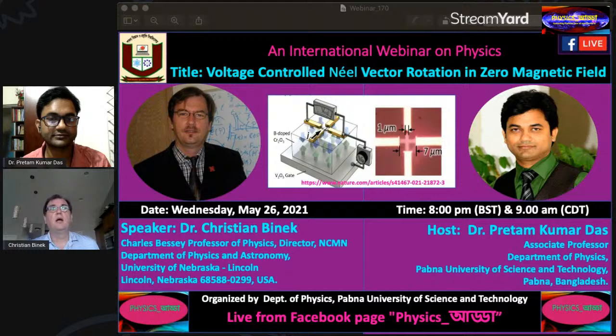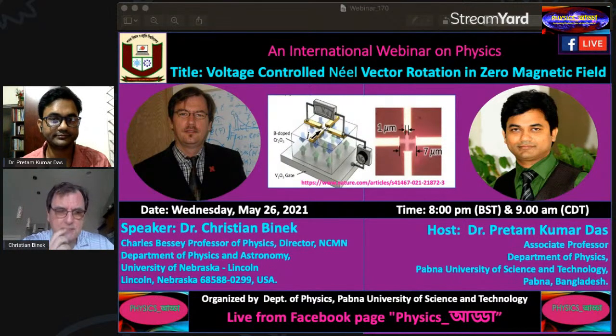Yeah, so, of course, I must admit, it's a bit special. First one needs to understand what exchange bias is. Exchange bias happens when you take an antiferromagnetic material and a ferromagnetic material, let's talk about thin films, and you bring them into close contact. Then the ferromagnet and the antiferromagnet interact at the interface. And then you get an emergent interface phenomenon, namely that the ferromagnet now behaves differently due to this interaction.